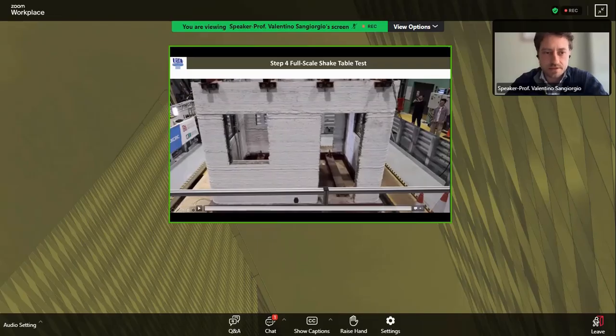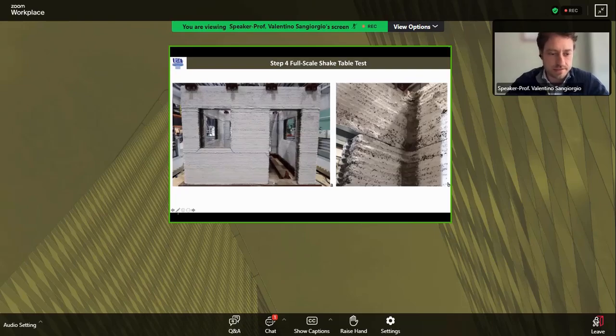Here, you can see a huge crack, and another crack occurring in this position. So here you can see what happened during the test. This is the upper crack, and here you can see a lower crack, one horizontal and some diagonal cracks that reached the opening.